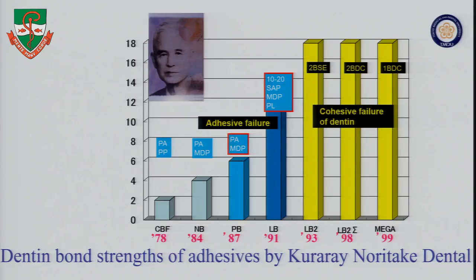So that's why we could not obtain a bond strength value of more than 20 megapascal with this kind of conventional test method. That's why we needed to develop the testing method named the microtensile test or micro shear test.